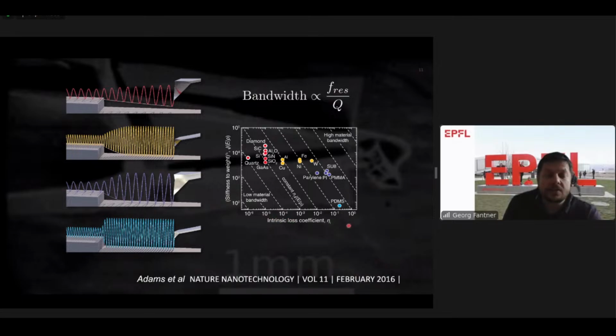And on the x-axis, we plot the mechanical property that determines the Q factor. So the property that determines the Q factor is the intrinsic loss coefficient of the material. And so all of these dotted lines here have equivalent bandwidth, so to speak, from a materials perspective. So if your material sits down here, your cantilever is going to be very slow, whereas if your material sits up here, it's going to be very fast.